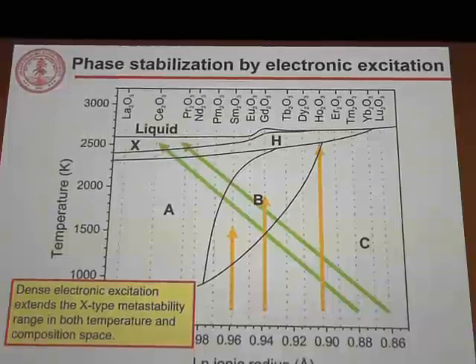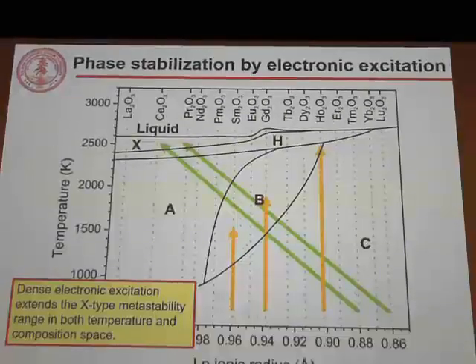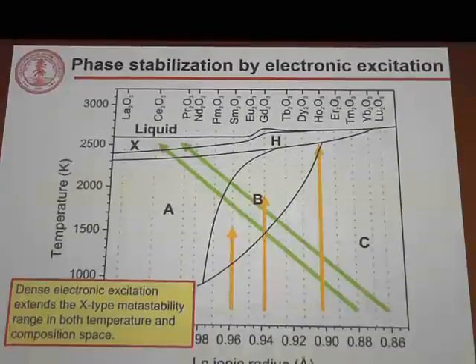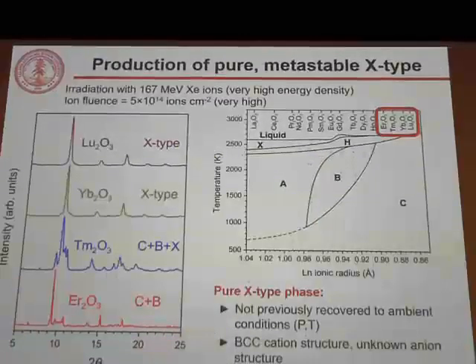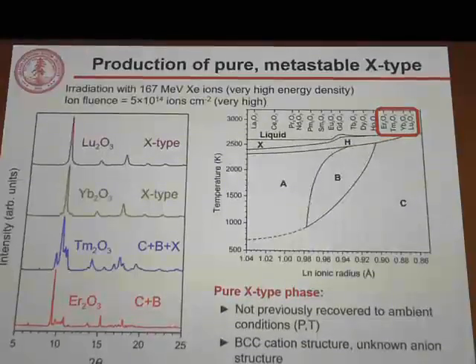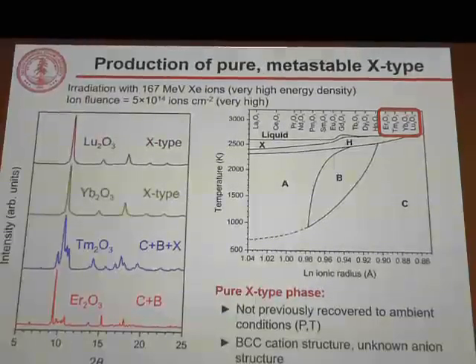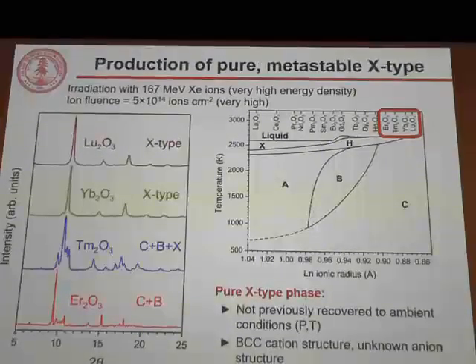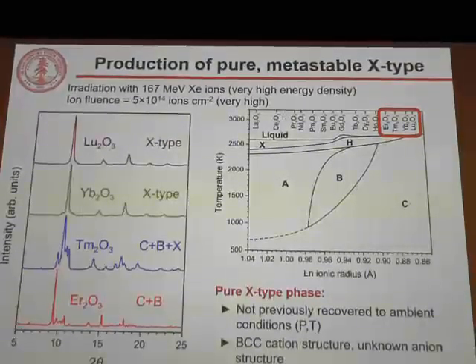And this shows us how extreme environment processing allows us to access new kinetic pathways and stabilize new phases. Now, the fact that we stabilize this phase is really interesting because when we tailor the irradiation conditions, we can make, for some materials, such as lutetium sesquioxide, a pure X-type material, which, again, hasn't been made before. We can now characterize the structure of this material, which wasn't well understood previously.